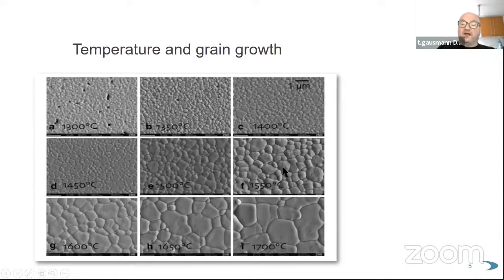When you go to 1550 degrees, you can see that the grain is growing. It's getting bigger and bigger. Like I said before, when it's getting bigger, it's getting more translucent. But when it's more translucent, it's getting weaker. Like with any material, you can have one or the other; you can't have a material that gives you everything. So in zirconia, you've got either something translucent or something very strong. That is just fact. Then you can see, I have to go back, that we've got 1600 degrees here. This is the temperature of Zirkonzahn, for example.